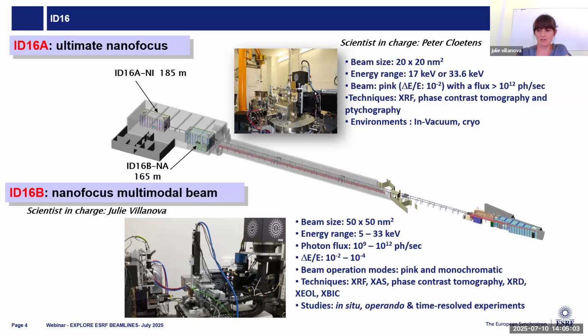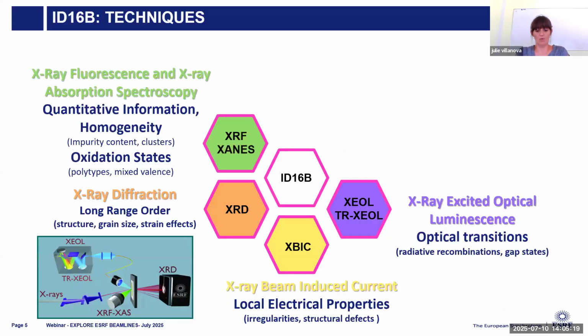As you can see on the image below, we have some space around the sample and we are working in air. So it means that we can accommodate sample environments in order to perform in situ, operando and time-resolved experiments. We have different techniques available at the beamline that I like to separate into 2 groups. We have what we call the scanning techniques, meaning that we raster scan our sample with this nano beam and record different signals. And we also have the full field technique.